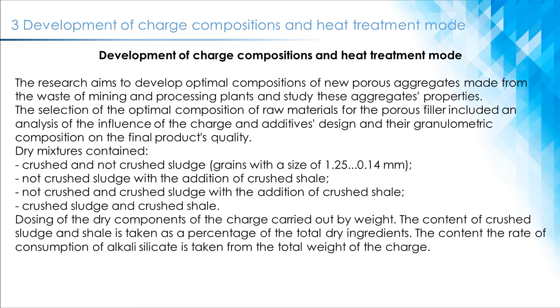The selection of the optimal composition of raw materials for the porous filler included an analysis of the influence of the charge and additives design and their granulometric composition on the final product's quality. Dry mixtures contained crushed and not crushed sludge, grains with a size of 1.25 and 0.14 millimeters. Not crushed sludge with the addition of crushed shale. Not crushed and crushed sludge with the addition of crushed shale. Crushed sludge and crushed shale.